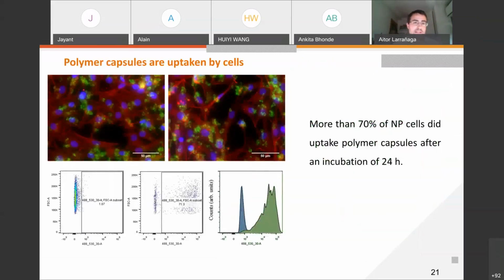We also wanted to check the interaction between our capsules and the nucleus pulposus cells. And for that, what we did was to fabricate fluorescently labeled capsules that you can see in these pictures in green. As you can see, it seems that some of the capsules are internalized by cells, and this result was further confirmed by flow cytometry, where we determined that more than 70% of the nucleus pulposus cells were able to uptake these polymer capsules after an incubation period of 24 hours. This result was quite interesting for us because we can expect our capsules to scavenge not only the reactive oxygen species that are produced extracellularly, but also the reactive oxygen species that are produced inside the cells.